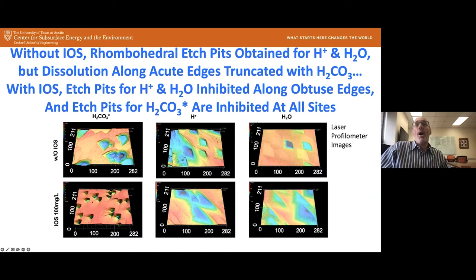For the proton and water, we get a really interesting effect. Here we see now we're getting these triangles, so no longer the classic rhombohedral shape, but these triangles, and so it's etching preferentially in the acute direction and not in the obtuse direction, or along the obtuse edges. And so what's going on there?